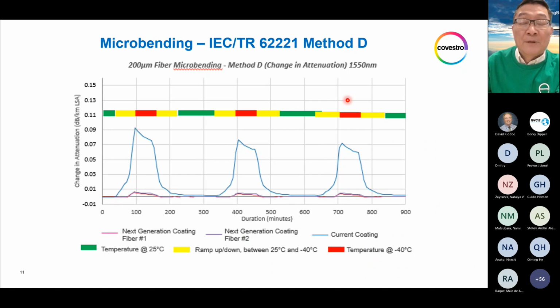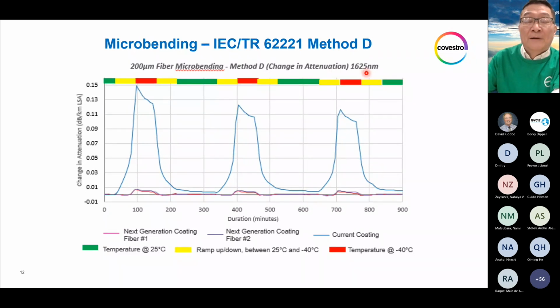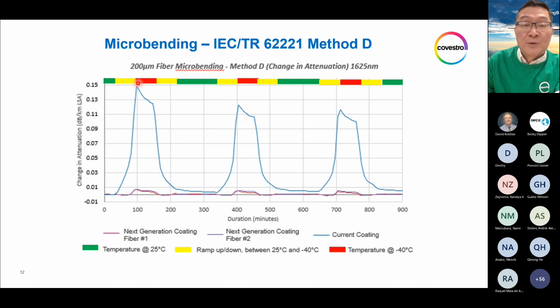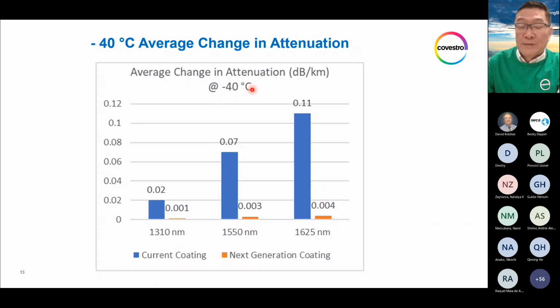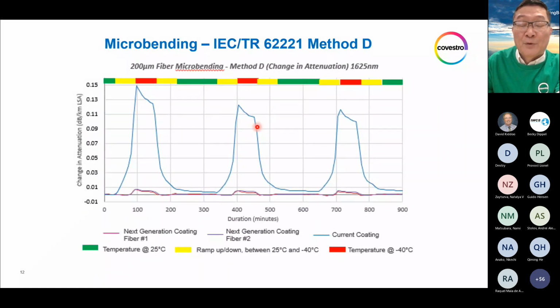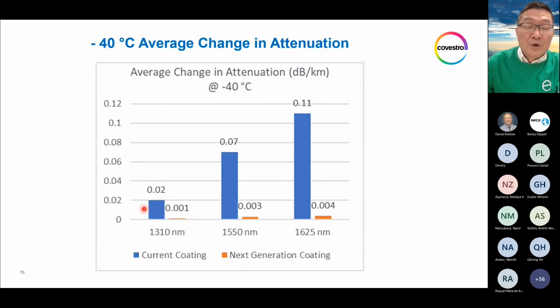However, the absolute value went up because it is well known in the industry that the attenuation absolute value goes up with the wavelength. And more dramatically at 1625 nanometer, the absolute value went up again, but we still see the same trend, that the next generation coating has a great benefit of reducing microbending loss. To summarize, we only look at the minus 40 degrees C range, these 3 regions, and take the average of 3 cycles, then compare the 2 systems, the current system in blue and the next generation system in orange, at 1310, 1550, and 1625 nanometer, the 3 different wavelengths.